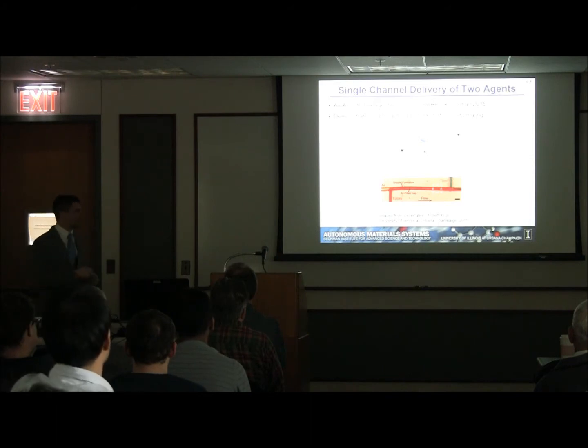What he did is he had a central channel which had high pressure, high velocity air flowing through it. And tangent to those, we had our liquid agents, the epoxy and the hardener, coming into the side and streaming into this main air line. And so the air that's moving at high velocity would actually shear these droplets off into the airstream and then deliver them to the crack plane as discrete droplets instead of as a continuous stream like what I had previously done with my double cantilever beams. And he was able to show significant improvements in the mixing using this.